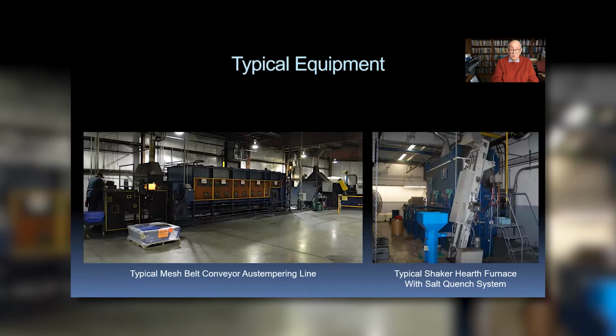A lot of parts are done in a mesh belt conveyor line. The one that's shown on the left, where parts are loaded onto a table, sent through the furnace, and dropped at the end of the furnace into a salt quench, which is located in the floor in this particular drawing. Salt is the primary medium that we quench parts that will be austempered in, because salt gives us the temperature range we need to be above the martensite start point.